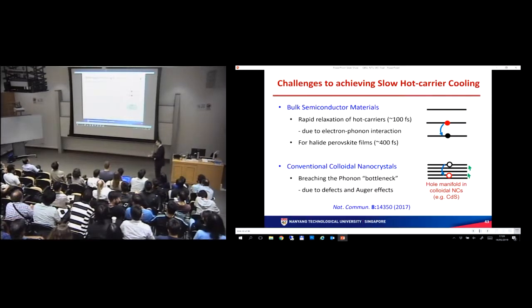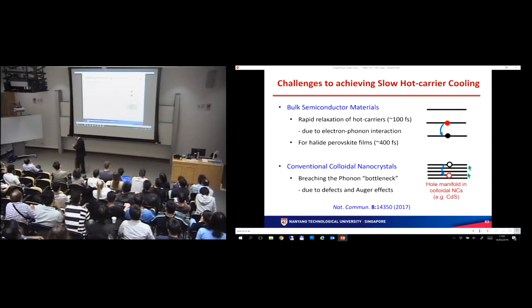Now, it turns out that as you shrink down traditional colloidal nanocrystals like cadmium sulfide or cadmium selenide, the phonon bottleneck is breached, due to various reasons, due to surface defects and Auger effects. So again, this concept of using the phonon bottleneck to slow down carrier cooling in traditional inorganic nanocrystals wasn't very successful.